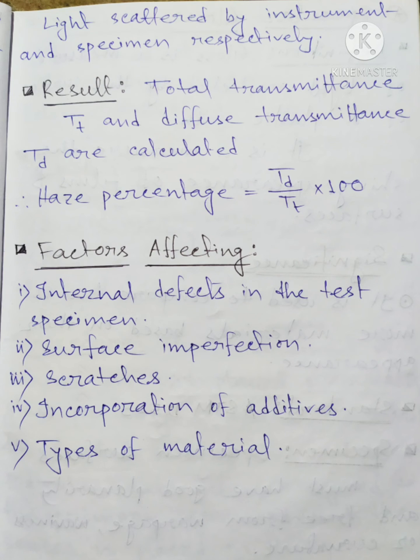If there are internal defects, light does not pass through properly. Surface contaminants such as dirt or oil also affect light transmission. Scratches cause light to reflect rather than transmit. Additives can create problems depending on the material — if the material is cloudy it shows higher haze, whereas if the material is fully transparent it has excellent clarity. Haze therefore depends significantly on the type of material.